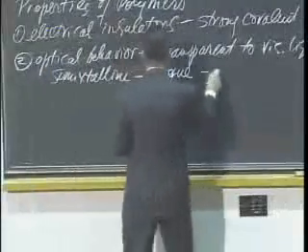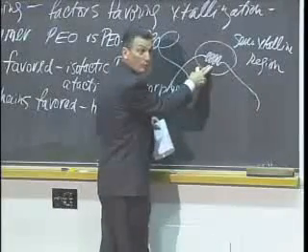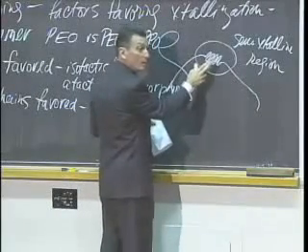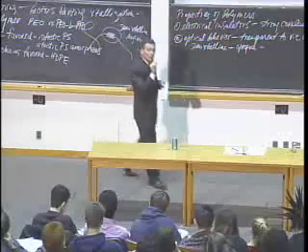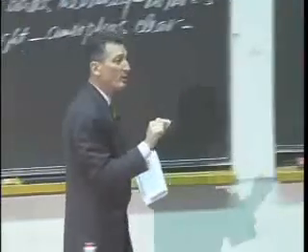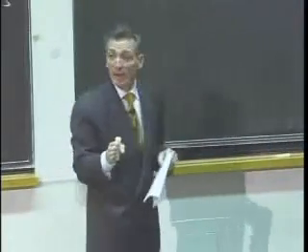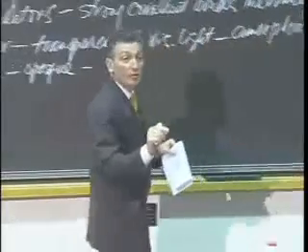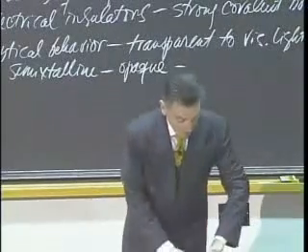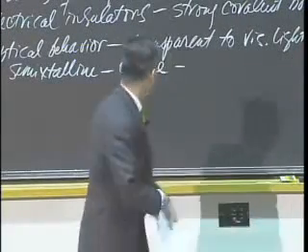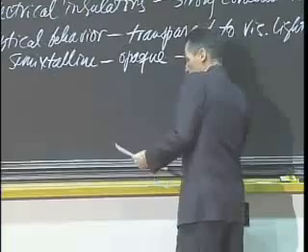Now the question you've got to ask is, could you generate semicrystalline zones that were either index matched or on a length scale shorter than that of visible light? We saw that in the inorganic case with the difference between Pyroceram glass and Visions. The only difference was that the crystallites in Visions were much, much smaller, and as a result we were able to get the strengthening effect without incurring the penalty of opacity.